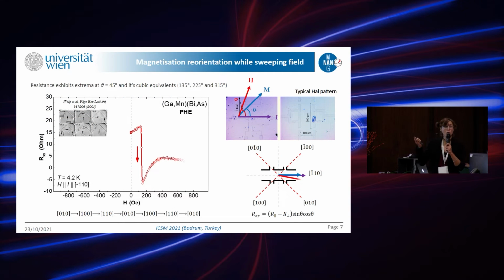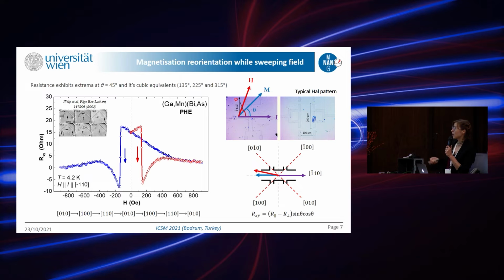Here you see how we were measuring. Everything was performed at 4.2 Kelvin, liquid helium temperature. We start by sweeping the magnetic field to plus 950 Oersted and minus 950 Oersted, and immediately the planar Hall measurement shows us 4 extremum points. The explanation we see is that magnetization is reoriented while we are sweeping the magnetic field, corresponding to 4 extrema. It's theta equal to 45 degrees in this equation, and its cubic equivalent.